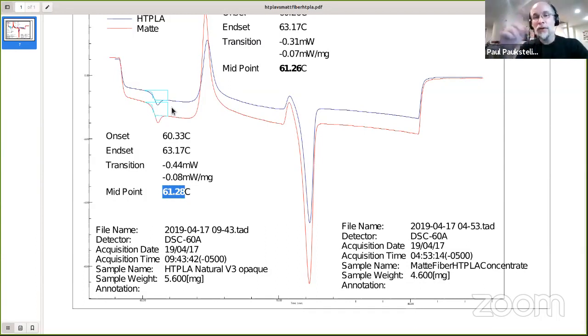But usually, when you do two melts, the first melt that you've done on an HTPLA will go through, because you're melting very slowly, you're going to go through that crystallization phase, which is right here, around 110 or whatever. So you will see a shift in where this melting peak is, whether you're on the first time through or the second time through, and the rate at which you actually heat the sample. So this melting peak will shift depending on that.